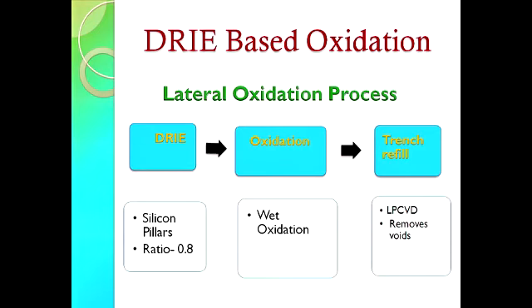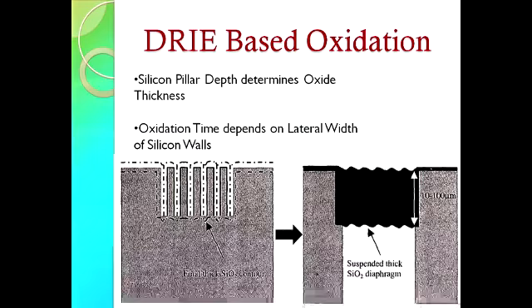Could you talk a little bit more about that membrane forming one? For this one? Oh, actually, what we can do is we can isolate the insulating material. So this is just to show we can isolate the material by back etching of the silicon. So here we had the silicon wafer, and it was back etched to form a suspended thick oxide.